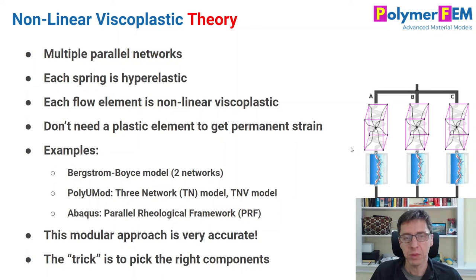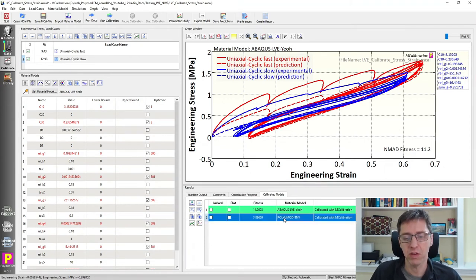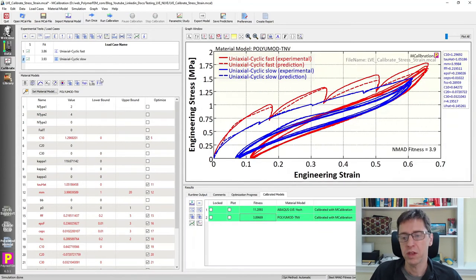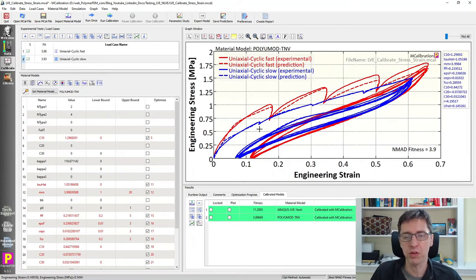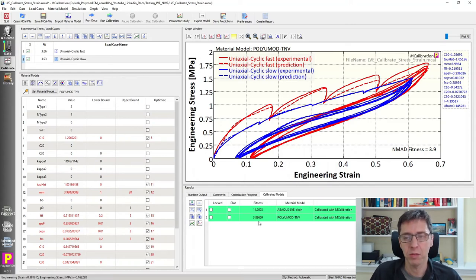Using our earlier experimental data — where the linear viscoelastic predictions were poor — if I switch to the three-network viscoelastic (TNV) model in PolyUMod and run it, the predictions are much better. The average error drops from 11% to less than 4%, and the model correctly captures both the initial modulus and the cyclic response. This is the kind of value enhancement you get by switching to non-linear viscoelasticity.